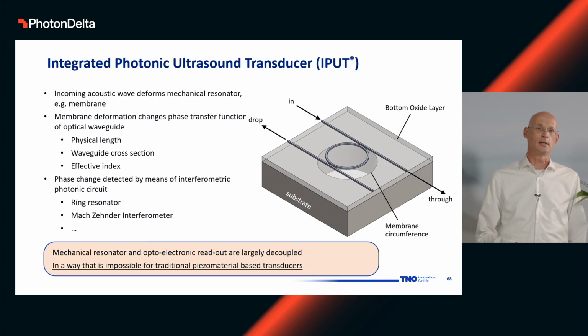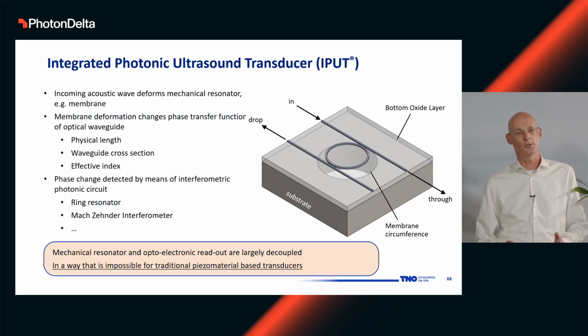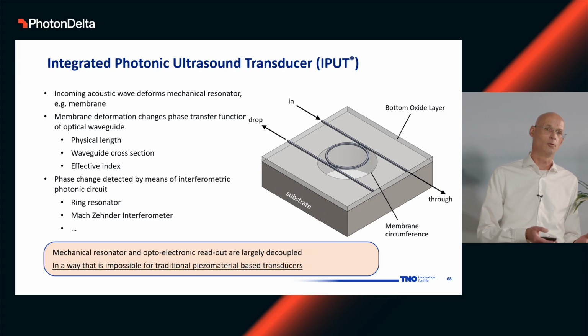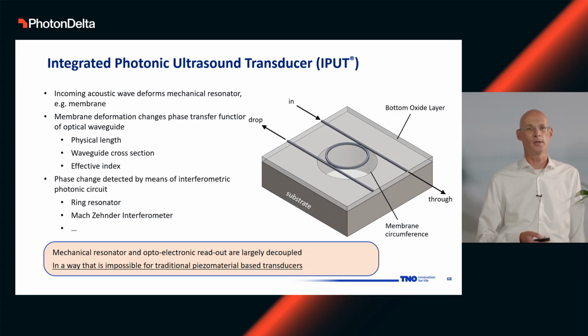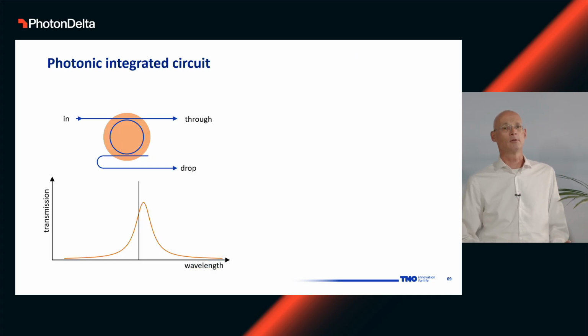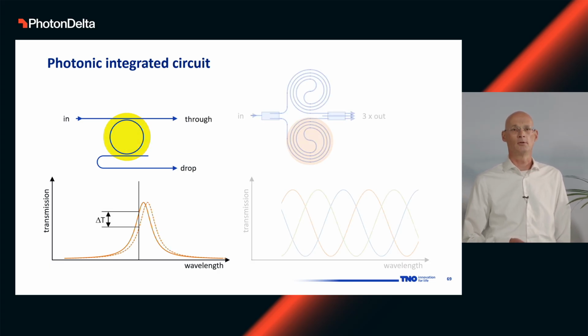Now, the key thing here is that the mechanical resonator, which is the membrane, and the optoelectronic readout, which is your system to read out the ring resonator, are decoupled, unlike the way it is coupled in the traditional piezo material transducers. So we believe that this is the way to boost the performance even further, because of decoupling, sensitivity, and noise. Now, one thing you can do is this with a ring resonator. Typically you can put a laser line at the edge of the resonance, and then when there's an acoustic signal, the resonance will shift.